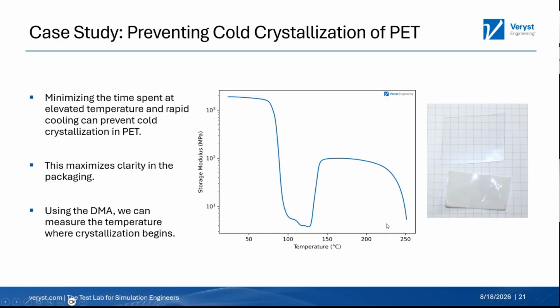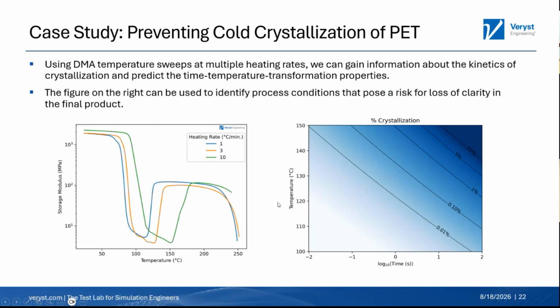And so just to dig into that a little bit further, this is a DMA temperature sweep on thermoforming grade PET. And you see something similar to what we saw in the DSC trace, where at low temperatures we have a very high modulus. It drops as we go through Tg. And then once we hit about 130 degrees or something like that, this material actually stiffens because we were forming those crystalline domains. And as we heat it up even more and more, it'll start to melt. Our modulus will start to drop off. So you can use a DMA to measure these types of things as well as a DSC. But in terms of more advanced applications of this technique, you can actually use different heating rates and you get different traces.